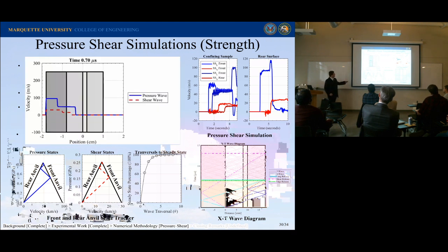So here I have a simulation. Here you can see the longitudinal wave, this blue wave coming into the sample, and then following right behind it is the shear wave. The shear wave goes through the sample next, and then you get the pressure wave coming off of the front, and you get the data, and then the shear wave comes off the back, and then you get the shear data. And so that's how you've measured the strength of material under pressure and shear.